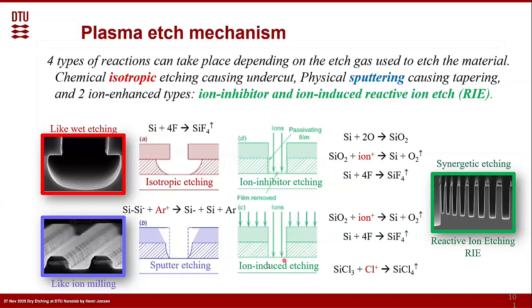Then finally, another type of ion induced etching, which is related to this one, is when you use not fluorine radicals, but chlorine radicals and ions. When you use a chlorine plasma, before, when you had fluorine, the fluorine radicals are so small that they can penetrate the silicon lattice. So they can even etch the silicon lattice from the backbones. Therefore, it is very spontaneous and easy to etch.